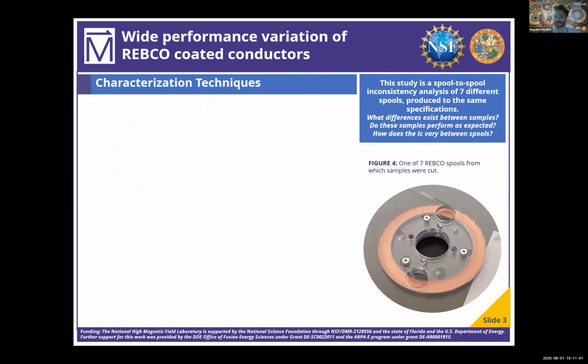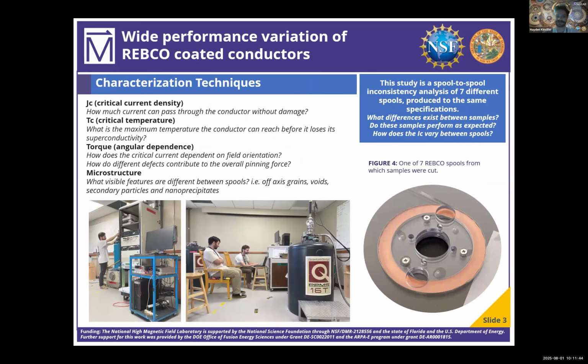So for our study, we started with 7 different spools produced by the same manufacturer to the same specifications. So theoretically, they should be the same. This is just an example of what the spools look like. And different characterization tests we did: critical current density, critical temperature, angular dependence, and we looked at the microstructure. So what did we find?